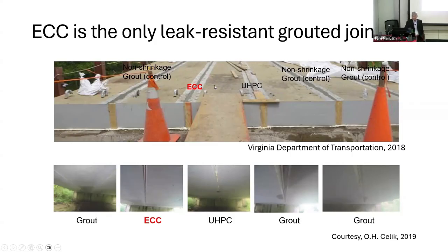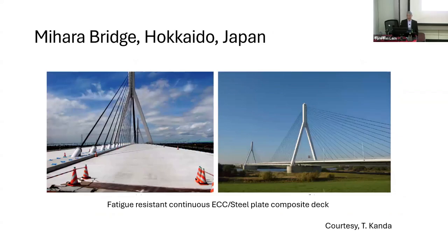It's not surprising. UHPC is very strong in compression, but in this application compression doesn't play a role. It's crack width control. Okay? It is shearing the keys, but shear in a 45-degree orientation turns into tension, diagonal tension. So this is obvious, you would say, and I agree with you. Once you have a problem with tension, it is tensile capacity, not compressive capacity.